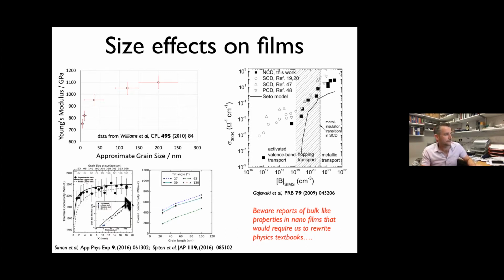Beneath, I've got the results from Martin Kuball's group in Bristol on thermal conductivity. And it's kind of the same story. You get below a certain size and the thermal conductivity just precipitates. It just drops completely. And this is physics. You can't get around this problem. The mean free path for a phonon in diamond is of the order of microns. So if your grain size is smaller than that, you do not have the thermal conductivity of diamond. And if someone is claiming they do, then we need to rewrite physics textbooks. So this is something you need to be very, very careful about.